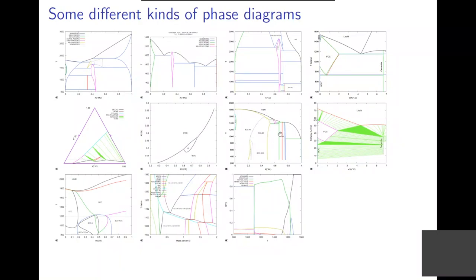This is an iron-aluminium system with a second order transition, which is sometimes a bit complicated to calculate, but the way OpenCalphad works, you can set as a condition the difference between, I mean, this is an ordered BCC phase, and the difference is that here you have different compositions on the two sublattices. Here you have the same composition on the two sublattices, but in OpenCalphad you can set that you should follow a line where the difference is a minimum value. So you can calculate second order transitions like this.